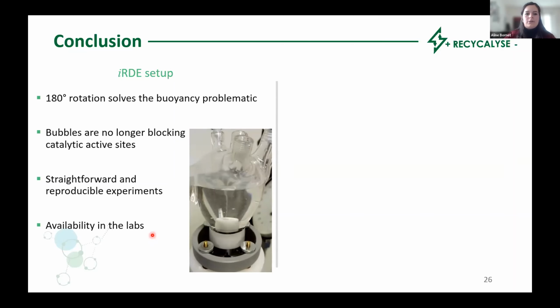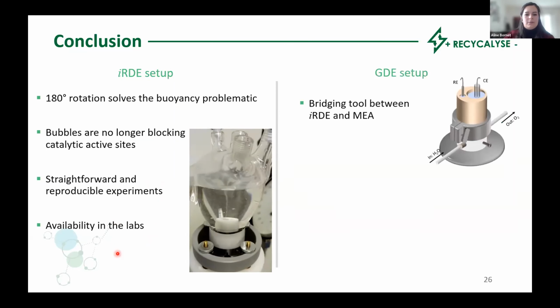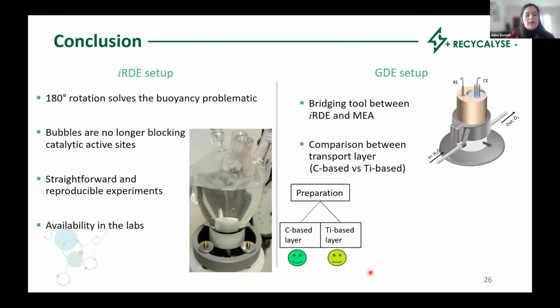But if we want to reach conditions closer to the real application, as is the case in Recycalyse, we need to use the GDE setup. And this is a suitable bridging tool between this inverted RDE and the MEA. It is quite simple to use, and still it can achieve conditions closer to the electrolyzers. And there I compare two options for the transport layers where the catalyst is deposited onto. One is the carbon-based and the other one is the titanium-based. And we saw that the preparation of the electrode is feasible for both. However, it's a bit easier for the carbon-based as we only need the vacuum filtration setup.